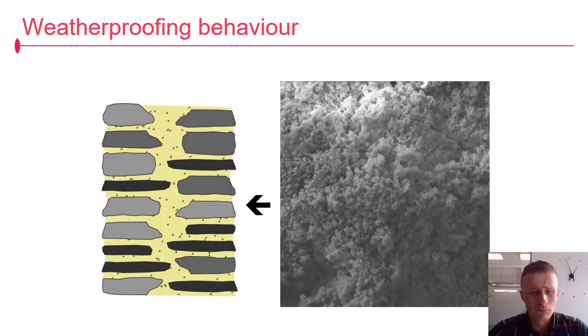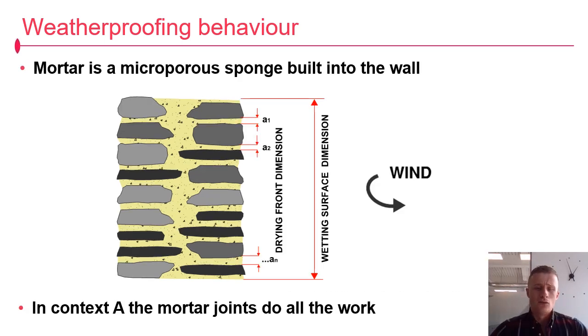When you look at lime mortar on a powerful enough microscope, it looks suspiciously like a sponge. So essentially you've got a load-bearing structural sponge built into the wall with a cold hairdryer blowing across the outer surface. That's what's happening. Non-saturated capillary flow, convective drying. Now, the wall gets wet according to its total area, but it can only dry in this context according to the total surface area of the lime mortar joint.